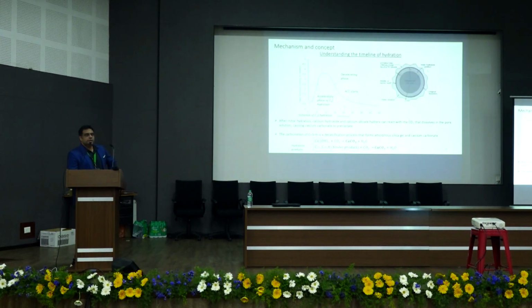The other technique which has found more applications or has drawn more attention, at least, is that of accelerated carbonation curing. And that can be done during manufacturing of concrete, during the curing stage, or even during transport of concrete members from the manufacturing facility to the site, right? Because it's a very quick process, happens within 4 to 6 hours. But before we go into there, we need to understand the hydration process, because the efficacy of this technique is dependent on the amount of carbonatable hydration product that forms in the cement.